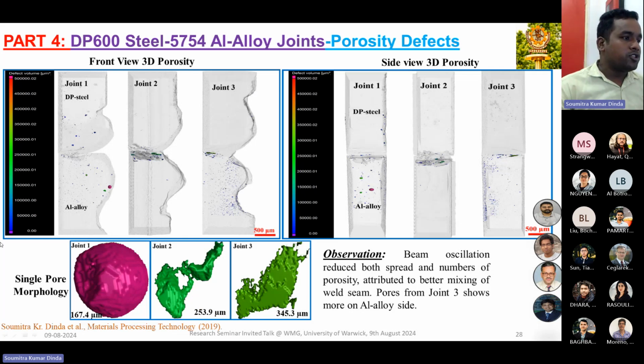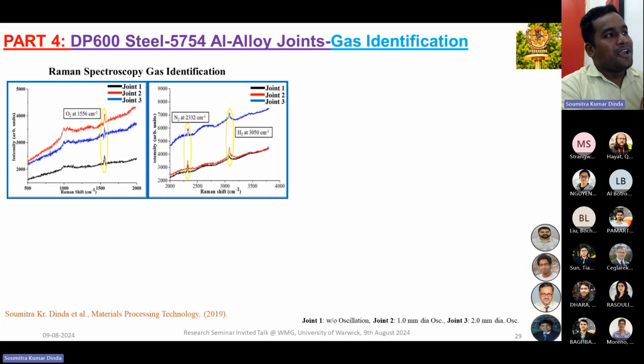And this is the individual pore geometry. Again we saw spherical pores, and joint 2 and joint 3 showing irregular shaped pores. Now, very interestingly, again we did Raman spectroscopy for the gas analysis. But in this case we did not find only hydrogen. We also found oxygen and nitrogen, and we found the peaks for all three cases. So we can say that the gas porosity formation is controlled by all three gases.